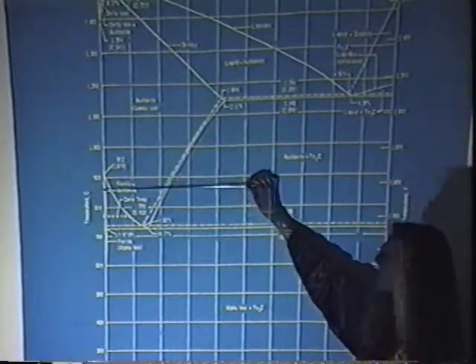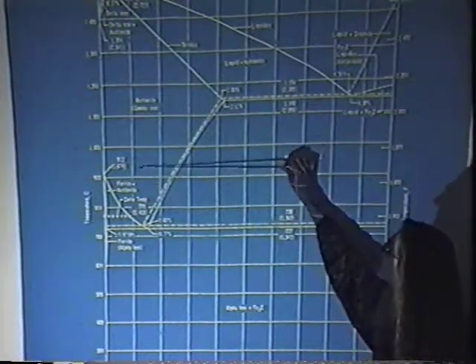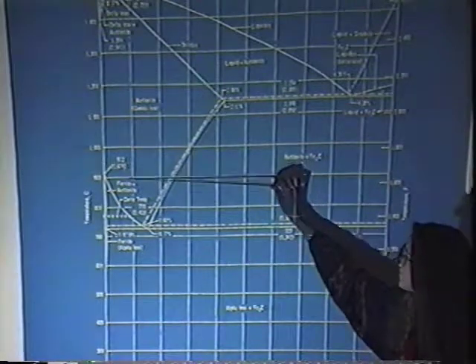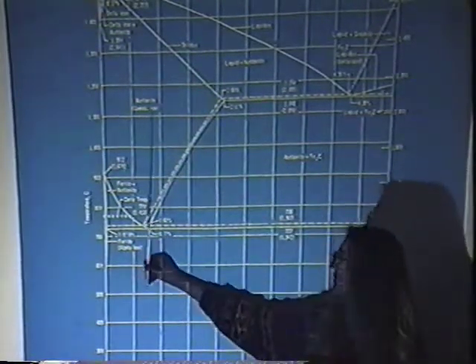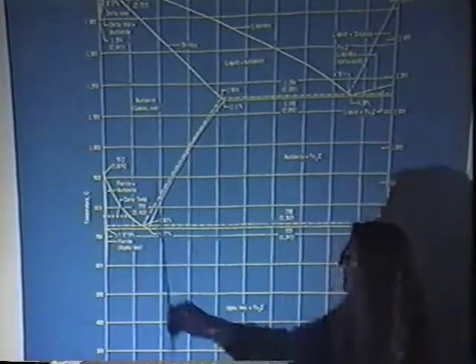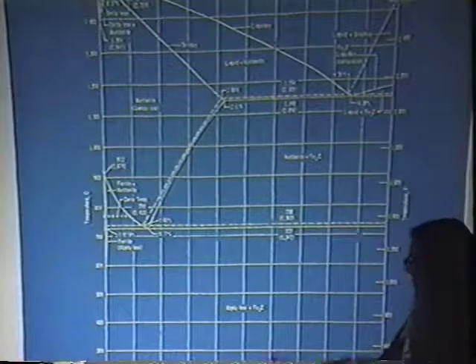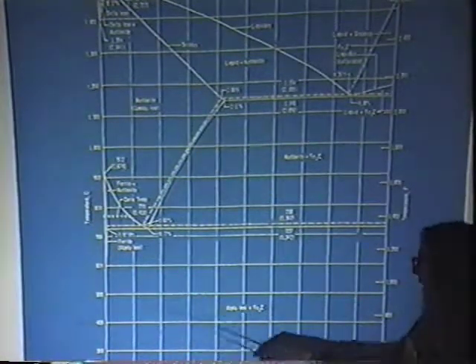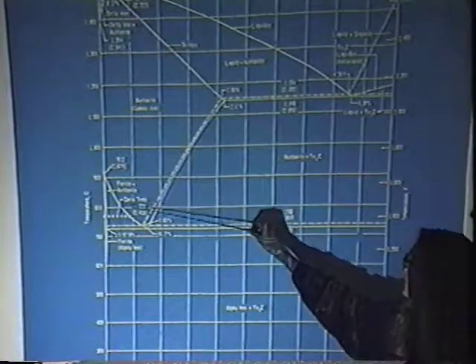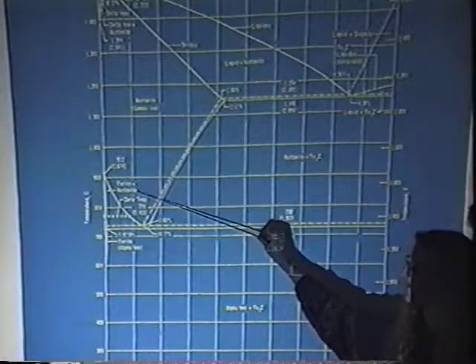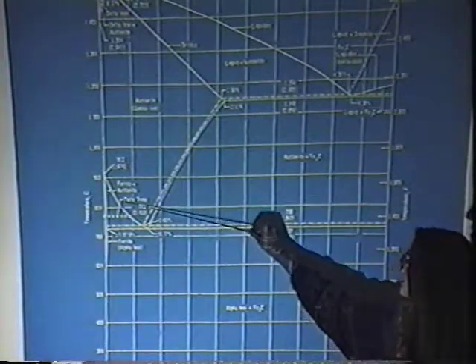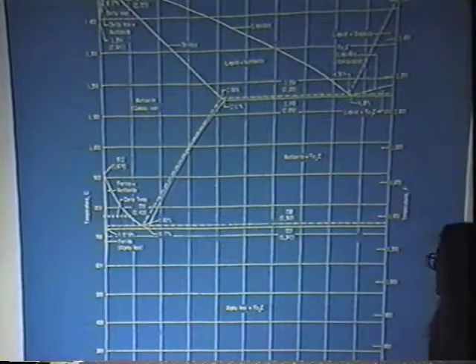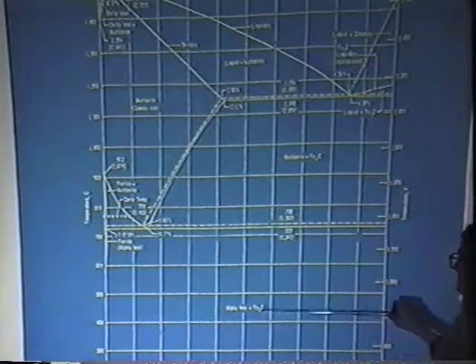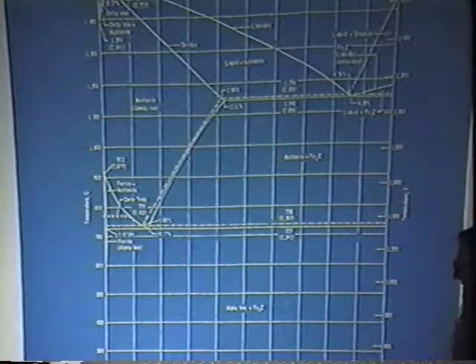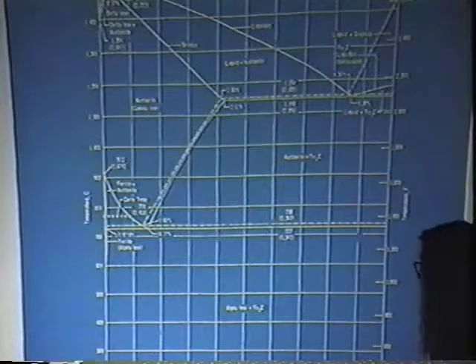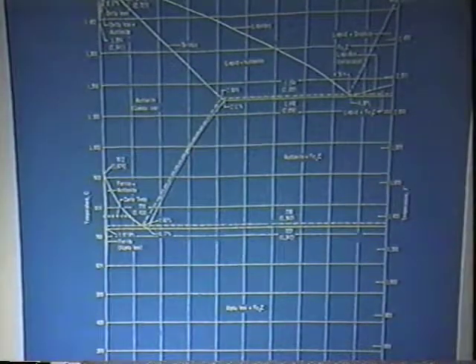So on this diagram, when we come out of the finishing stands, we're right in here somewhere. And as the steel cools, all of our steels that we run in the hot mill are within this box here, in this column. The carbon percentage is along the bottom. This first line here is 0.5% carbon. We don't run anything that high. As the steel cools, you'll see this little area here is called ferrite and austenite. There's where the first phase forms, ferrite. And then we go through this, the beginning of the transformation, and when we get done, we have pearlite, Fe3C. For the metallurgists that are familiar, you know what I'm talking about. For others, it's quite a stretch. I understand.